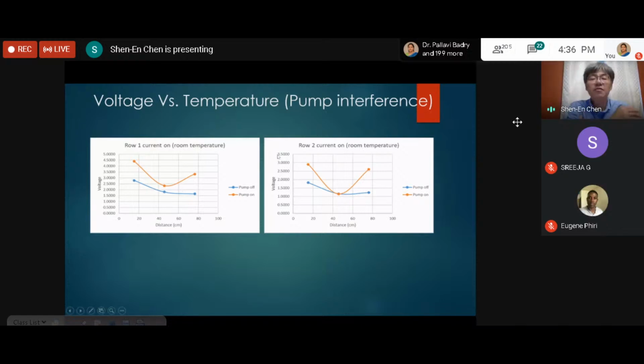Okay, and this is another thing that we found. So when the heat pump was on and off, the EMF interference to our experiment is visible in our measurements. So that's one of the limitations of this technique: because you're measuring the voltage change, any large power systems surrounding your measurement technique need to be avoided because they would interfere with your voltage measurement. And which can be avoided by shielding, but we currently are still learning how to shield those kind of EMF